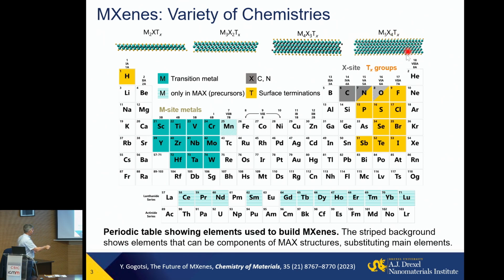But definitely the surface chemistry to a very large extent determines the properties, and we can get all halogens, chalcogens, oxygen, hydroxyl group, amino group, phosphorus, antimony. We predicted computationally arsenic is also possible. It's just a matter of going to make it here. And they come in 4 basic structures. This one we discovered with my students just a couple of years ago. So if you take 4 structures, a dozen transition metals, carbon, nitrogen, and a dozen surface terminations, you end up with about 1,000 simple combinations of these elements from which you can produce stoichiometric materials.